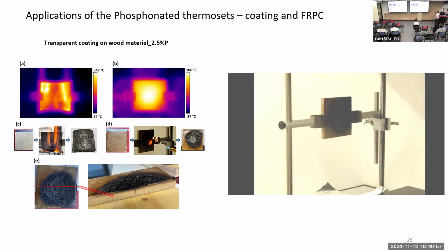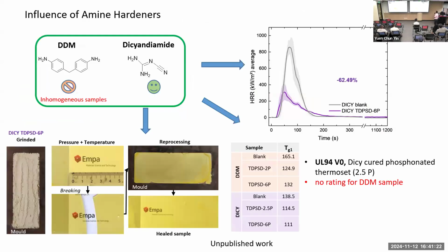Whereas for an untreated wood, which has no coating, you can see it just burns through. So it's a very nice example of how to use this kind of resin. And the fact that it is transparent matters, because for many wood applications, you want to see the structure of the wood. And that is where it is very interesting, I would say. You can have transparent and very thin coatings, I would say, which protect the wood.